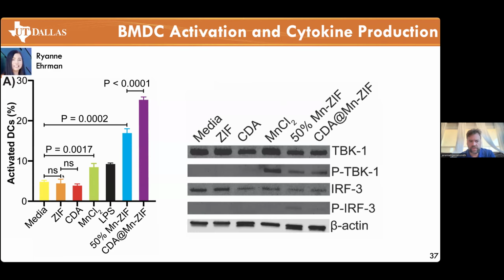And just zinc by itself doesn't really do much. CDA, the STING activating material, doesn't do stuff. The ZIF doesn't do anything, largely because it's not really immunostimulatory for dendritic cells per se. The CDA just doesn't get into cells, whereas the manganese, you can see, does activate the cells, as does lipopolysaccharide. The 50% manganese ZIF does significantly better. And when you add the cyclic dinucleotide to the manganese, it synergizes and you get much higher dendritic